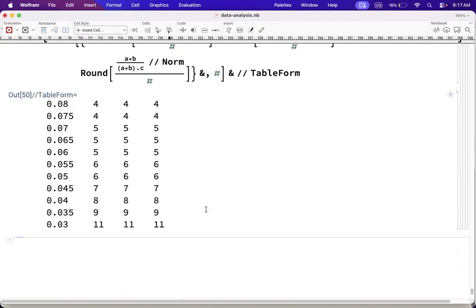Remember, in our calculations, we found that the grid that converged the total energy was 0.025. So this delta K is very important because we're going to use exactly the same delta K in any kind of system that we are going to use from now on.